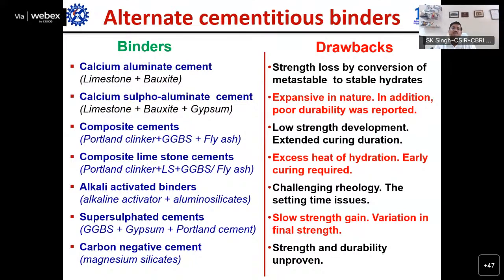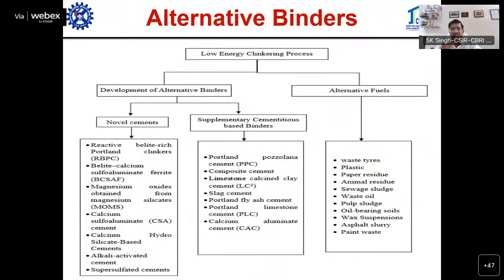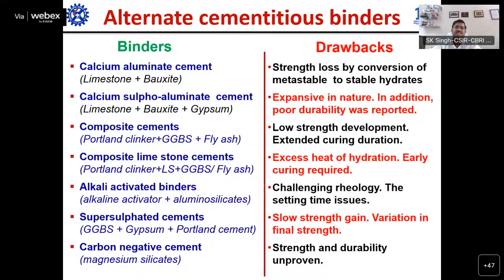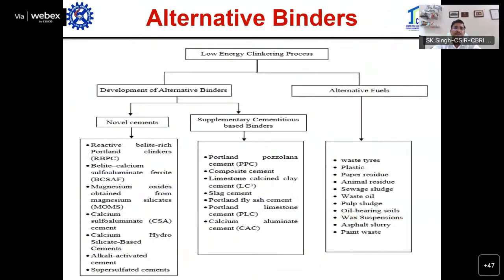And also, particularly, we are making cement by activating it, and several others, using lime sludge and GGBS with calcined clay. We have developed a cementitious binder in the laboratory. All those cements have some drawbacks, which have been looked into, but we are continuously improving them in the laboratory, and maybe very soon we will have a bigger trial in the field. We are already in touch with UltraTech Cement and other cement industries for that.